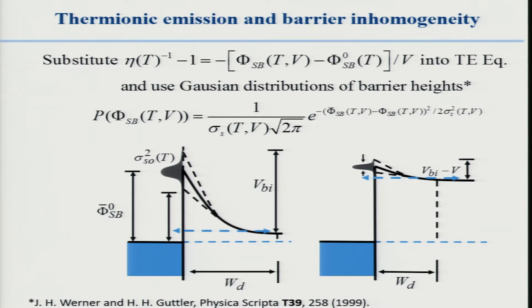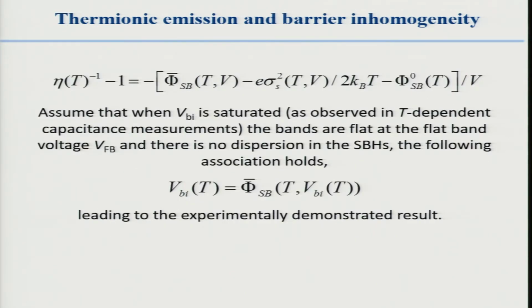And when you bias it in the forward direction, this distribution has a temperature dependence, and it becomes narrower. And eventually, when you go to high enough voltage, you get to what's called a flat band condition. That's the true barrier height. There's no curvature left, and electrons are just pouring over the barrier. We can't go up that high because we run into our series resistance. Okay. So here's the substitution you make into the thermionic emission equation.